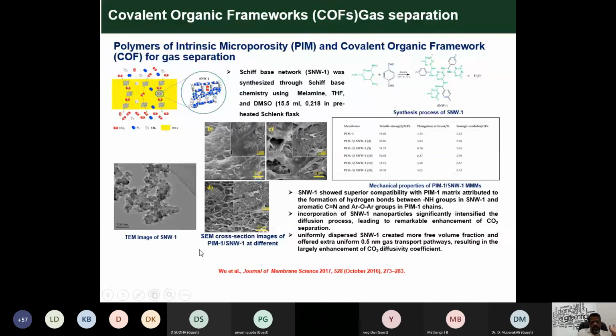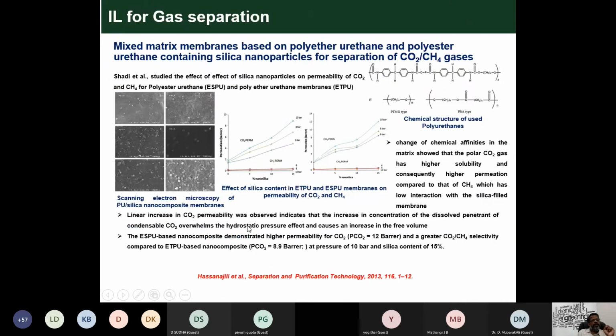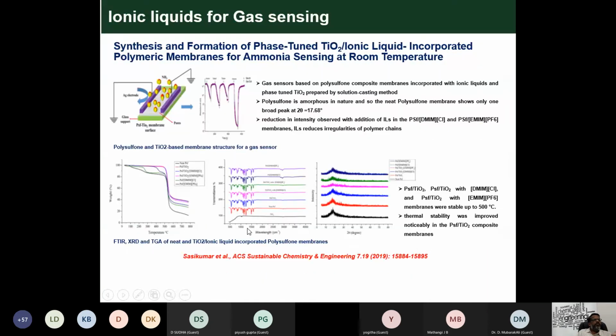Then we are working on it. We compared the performance of MOF and COF related materials, so there is no doubt COF is a very good material. They have different networks, and the network leads to different kinds of transport properties. They create more free volume fractions offered by uniform gas transport pathways, resulting in a large enhancement of the CO2 diffusivity coefficient. That's the reason. So COF is planned for gas separation, and similarly the same work for ionic liquid.